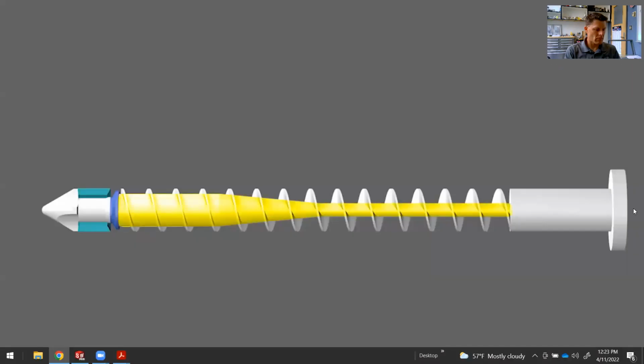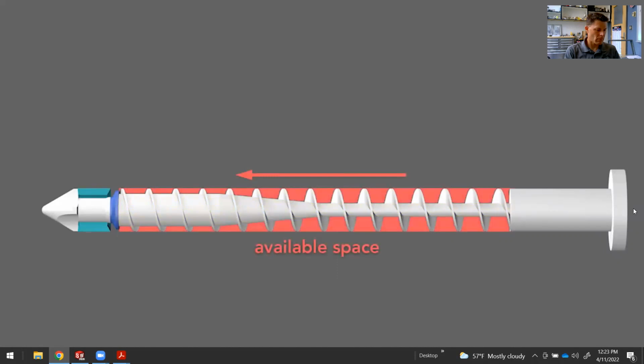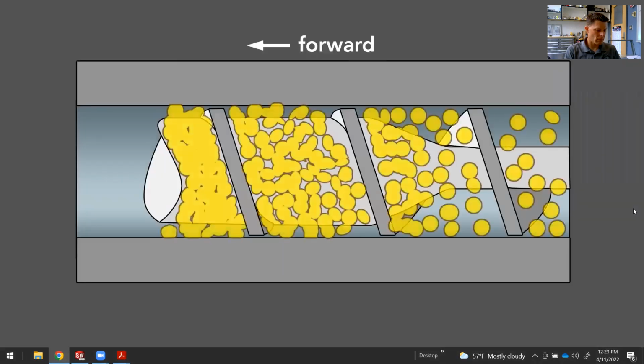The shaft's diameter increases along the screw so that the distance between the wall and shaft decreases. The flights then squeeze out air as they move the plastic forward, and they shear the pellets and press them against the barrel's wall. This shearing creates friction and so heats the plastic throughout. This screw-induced shear supplies a majority of the heat needed to melt the plastic, between 60 and 90%, with the rest from the heater bands.